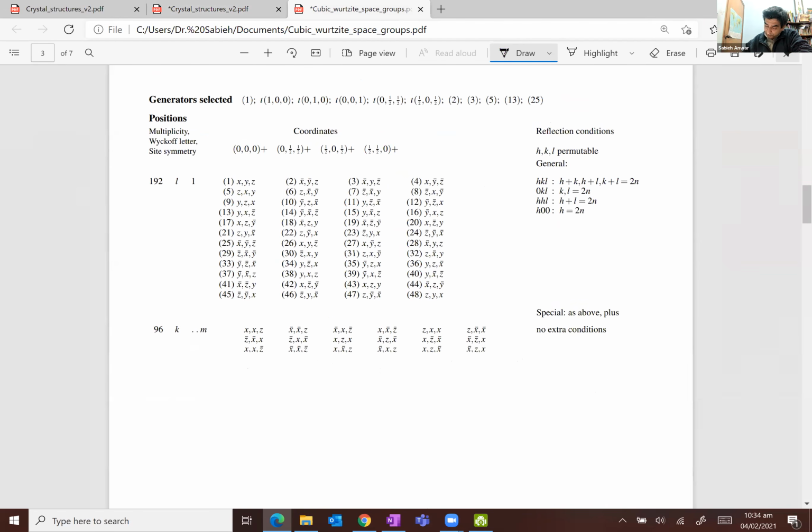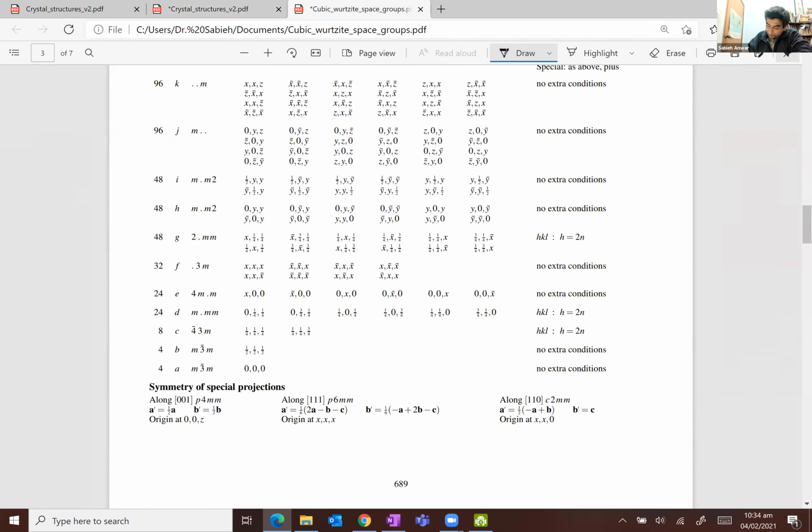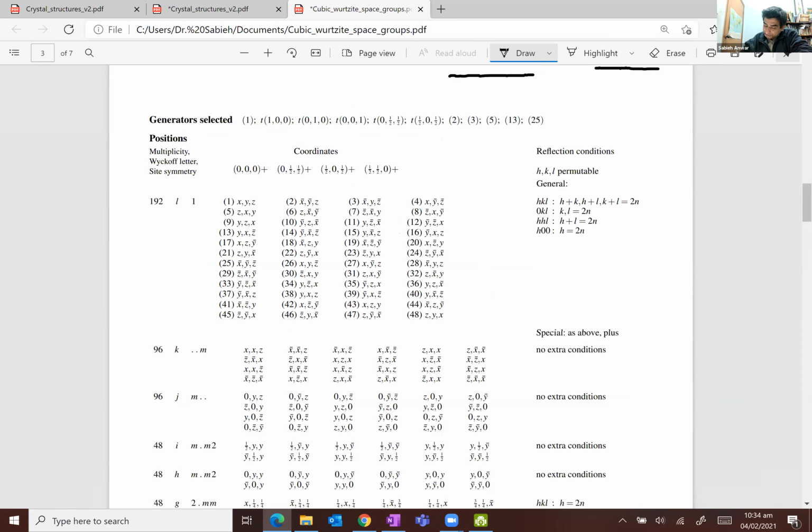So for the case of copper, we have one atom at the location 0, 0, 0, and three more atoms at these locations, which represent the center of the faces. So there are four copper atoms per unit cell, and there are 4 points in the lattice per unit cell as well, and there is one atom per lattice point. This is how the structure of copper is built.